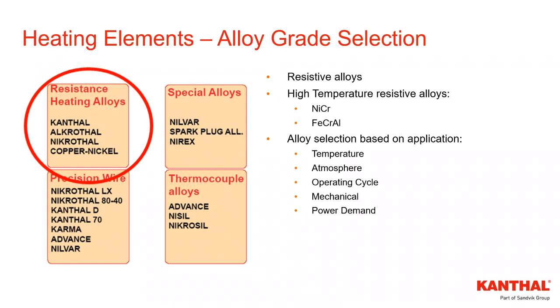And the high temperature resistive alloys essentially fall into two categories, or two groups. You have nickel chrome, or Nikrothal as we call it here at Kanthal, or iron chrome aluminum, or Kanthal alloys. And there are various grades within each of those groups, different grades of nickel chrome and different grades of iron chrome aluminum. And then you also have alloy selection. It's based on the furnace or the application requirements.